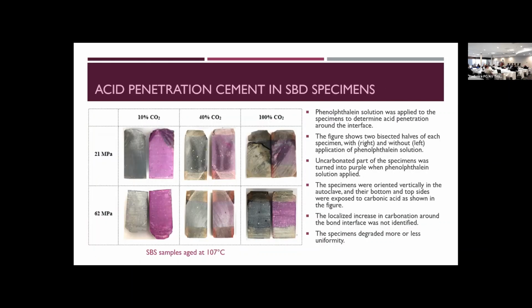In order to look a little more at the CO2, or if you want acid, penetration in the cement and how this looks, we use the standard phenolphthalein solution that is applied to the specimen, and by looking at the color we are trying to get an idea about how deep and how fast this will penetrate into the system.